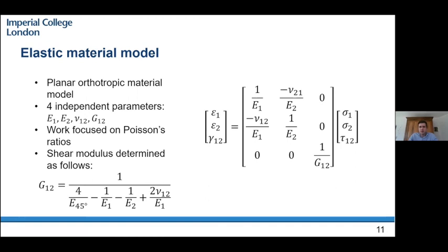This model consists of 4 independent parameters, 2 Young's moduli in the 0 and 90-degree direction, Poisson's ratio and shear modulus. This work focused mainly on the Poisson's ratio, but also determined the shear modulus, because the shear modulus is really difficult to measure directly. So we found a relation between the different Poisson's ratio and Young's moduli to get the shear modulus, where essentially you need a measurement at 45 degrees. That's also why we did this measurement of our coupons.